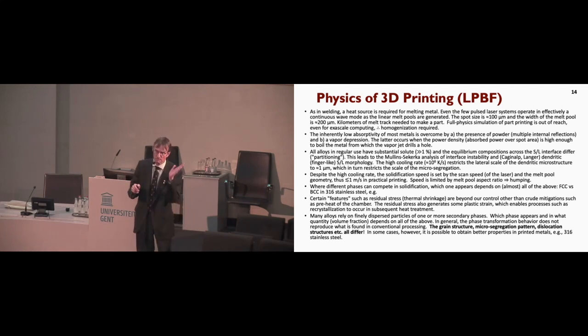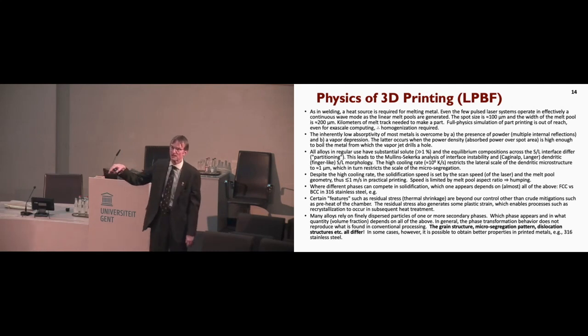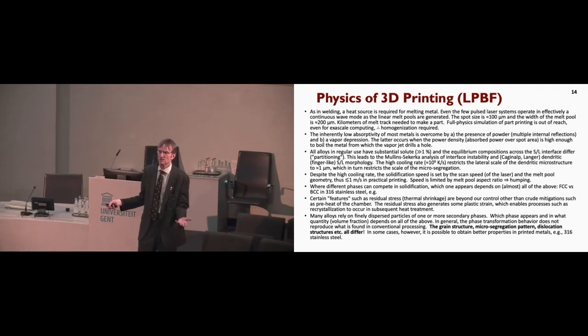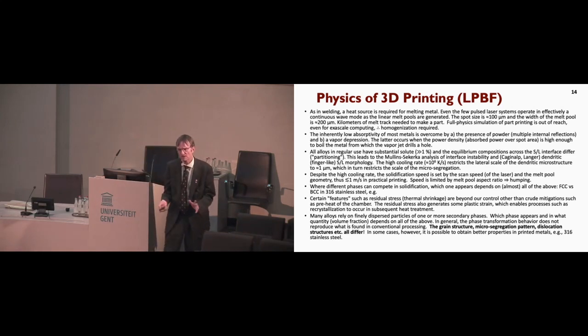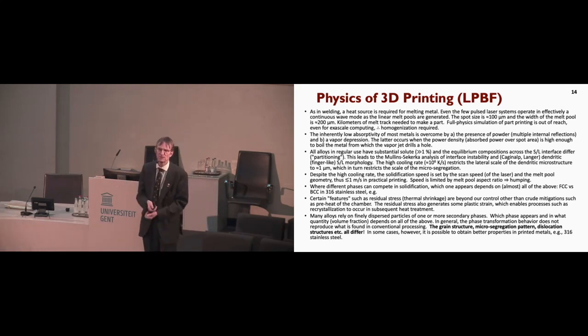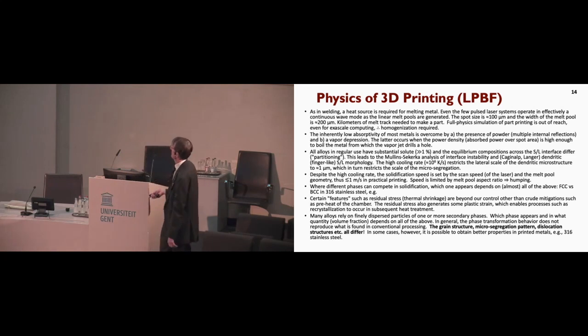The actual solidification rates are quite a bit lower than that. And in fact, one is limited at the upper end in speed. I'll come back to that. And so in many of the alloys we care about, you still get the same microsegregation. And that's very important. You still have Mullins-Sekerka instability. You still have microsegregation despite the columnar morphology. And that has a lot of impact, which I'll have to describe another day, on things like precipitation sequences. So that's pretty important.